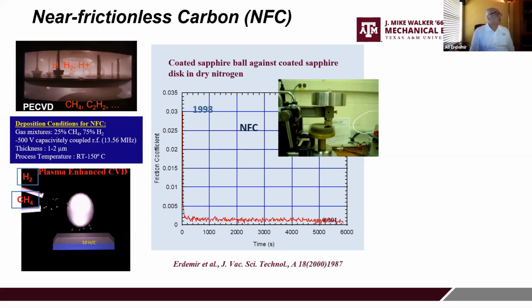So what we did was observe a very unique correlation between the amount of hydrogen that we put in the DLC versus their friction coefficient. We further optimized this to achieve a unique chemical composition resulting from 25% methane and 75% hydrogen in the plasma environment. The DLC film grown in this plasma environment gave a friction coefficient down to the 0.001 level.